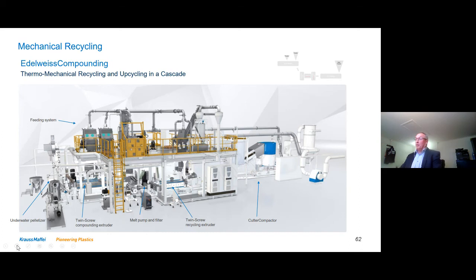So thin films can be processed here, but even expanded materials like EPS and other polystyrenes which were used for packaging materials. The extruder has a vacuum degassing, a melt pump followed by a melt filter for recycling, so a laser filter. At the end of the line we have an inline viscosity meter or rheometer. On the first line we can have underwater pelletized material coming out, or we bring via a melt pipe the melt stream into the second extruder, where we can add reinforcing, mineral fillers, polymers or further additives needed to come to a final compound quality to be used in the final step of processing. Next slide, please. 2 minutes, Jan, if possible.